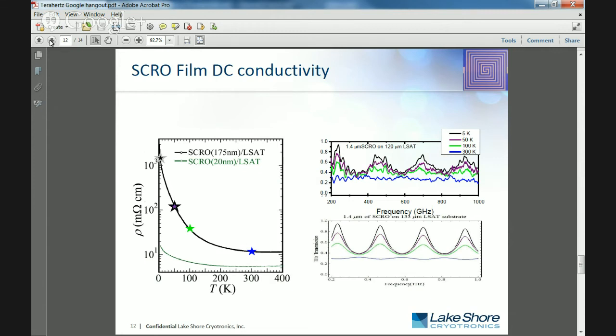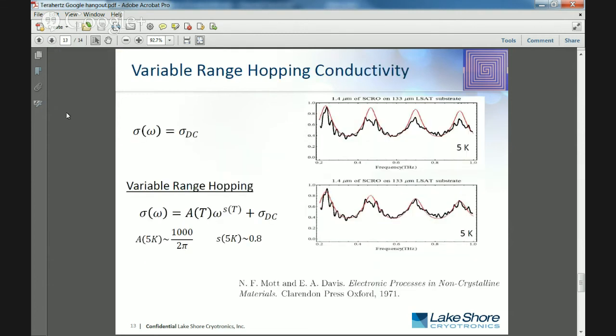We pop over to the slide that follows, and at low temperature, we actually have something a little bit different. We find something interesting in this case. If we just use the DC value of the conductivity in there, at higher frequencies, there's actually lower Terahertz transmission than at the lower frequencies. And what this tells you is basically the film is more conductive at higher frequencies than it is at lower.